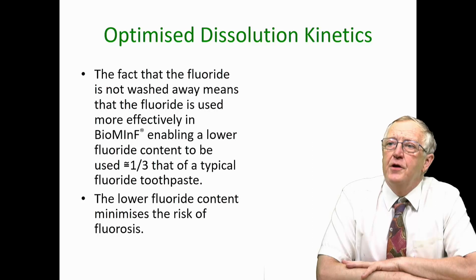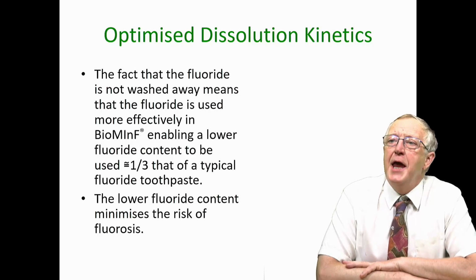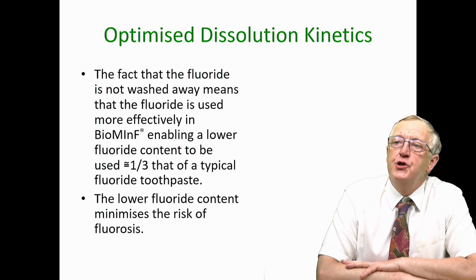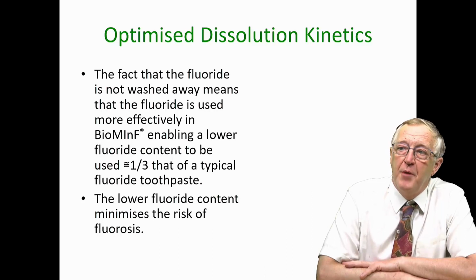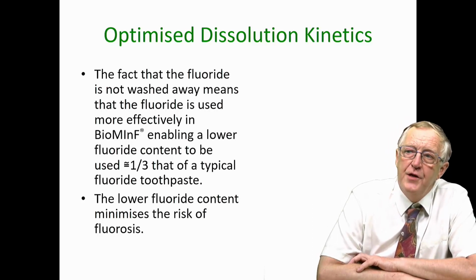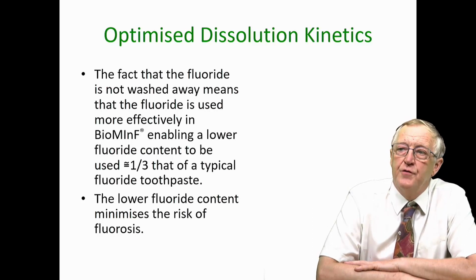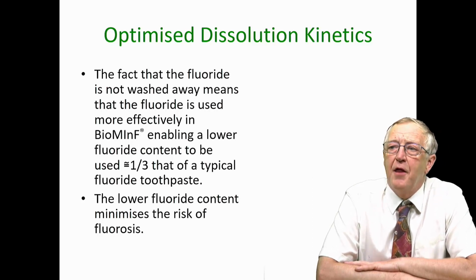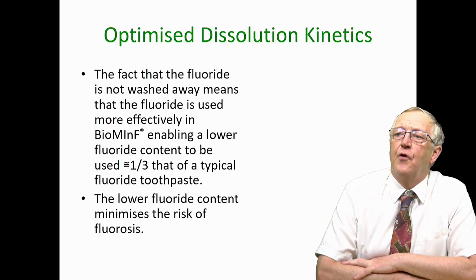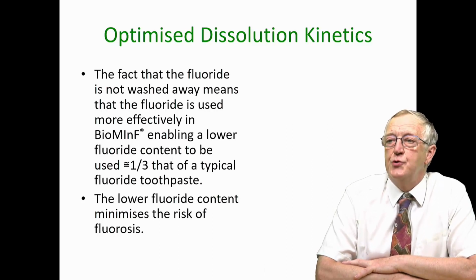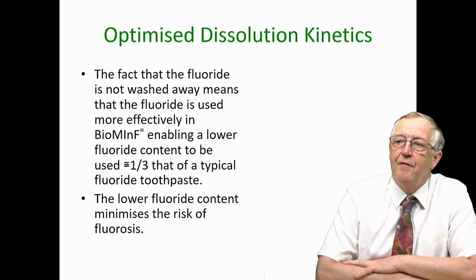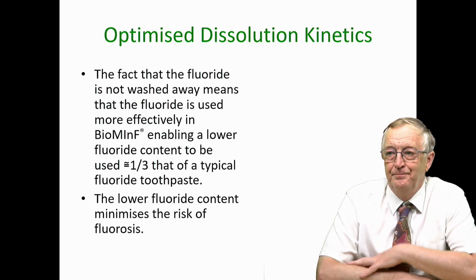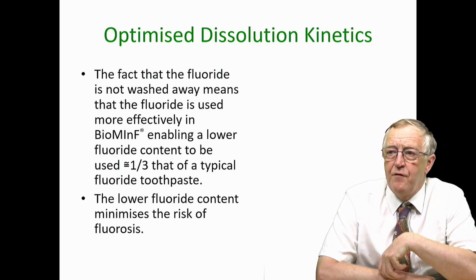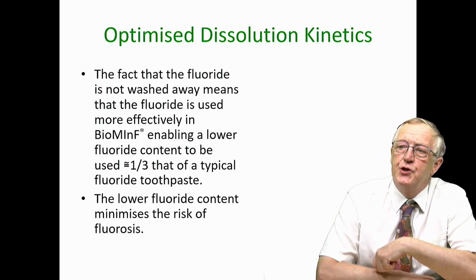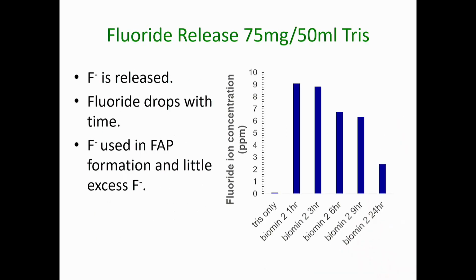The fact that the fluoride is not washed away means the fluoride is used much more effectively in the Biomin F toothpaste, and this enables the fluoride content of the toothpaste to be reduced, and it's typically about 1/3 of that of a typical fluoride toothpaste used in Europe. So it's about 500 ppm. The lower fluoride content reduces the risk of fluorosis.